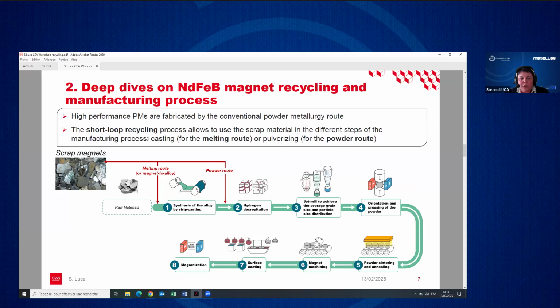So concerning the short loop recycling processes, the short loop recycling processes signifies that scrap magnets can be introduced in the different steps of the manufacturing of the magnets. So the high performance permanent magnets are manufactured by the conventional powder metallurgy route, which means that we fabricate an alloy by strip casting. This alloy is pulverized, the powder is compacted, then densified by sintering. An annealing heat treatment is applied to enhance the magnetic performances. Then magnets are machined, are coated, and then included in a system where generally we magnetize the magnet.